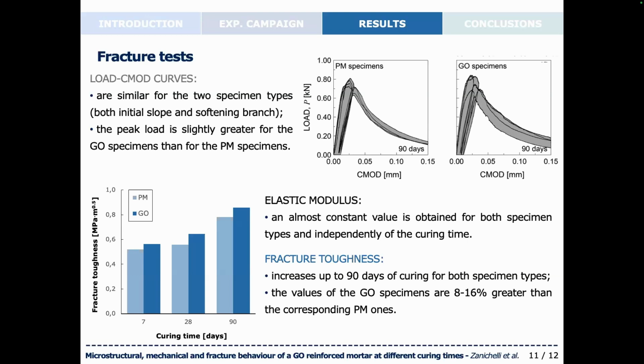load. And then by employing the modified two-parameter model, as I said before, we computed both the elastic modulus and the fracture toughness. For the elastic modulus, we obtained almost constant values independently of the specimen type and of the curing time considered. Whereas in terms of fracture toughness, we obtained an increase up to 90 days of curing for both specimen types, with the values of the GO specimens always higher than those of the PM ones.